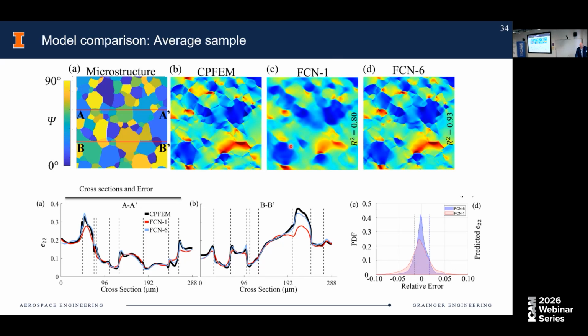And even the first network, as you can see, is not too bad. But if you look at these line scans, here is where you will see the difference. This is strain as a function of that cross section, and all the dashed lines are grain boundaries here. The ground truth is the black line, which is crystal plasticity. The original network is actually pretty good, better than anything I thought it would be initially going into this. But as you can see, it underpredicts some of the peaks, most of the peaks, actually. Whereas when you add the other elements, it's not right on, and you can see a distribution here of the error. But it's a significant improvement.